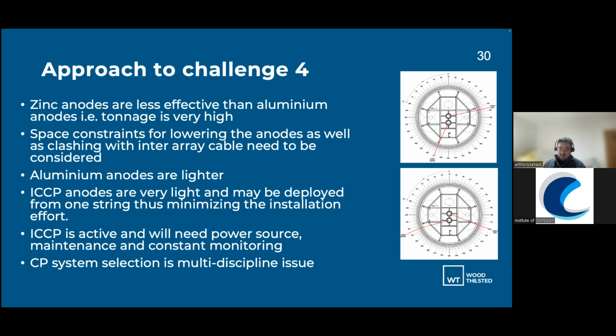Another way that we're trying to alleviate against that is to potentially use ICCP, which is much lighter and more flexible in terms of deployment. As I say, the downside is we do need power, and that's something that we need to consider in terms of how to manage, especially if there is any downtime in the power supply. But essentially, a lot of the issues that we're seeing are very much multidisciplinary. We don't see it just from a corrosion point of view. We have to see it from a secondary steel design, cable routing, met-ocean conditions, the geotechnical design. So I think it's a point that I want to bring across, that CP system selection is very much a multidisciplinary issue.